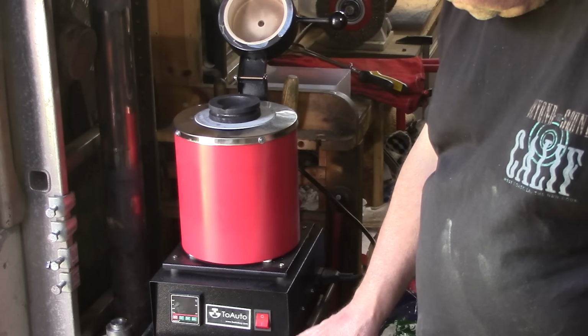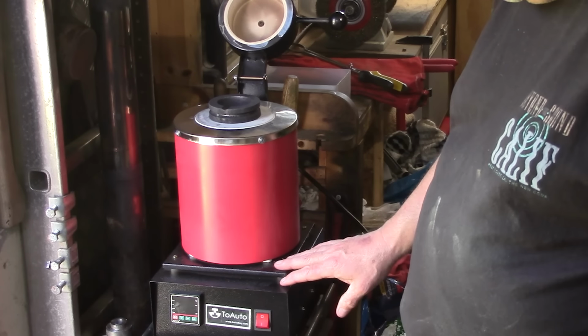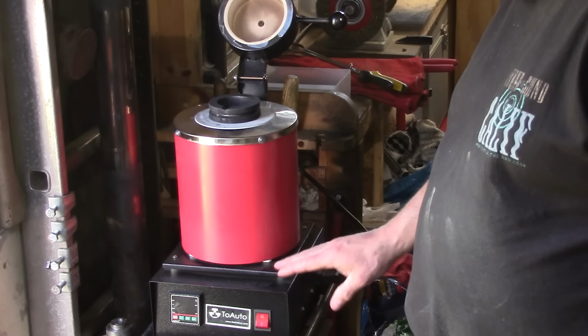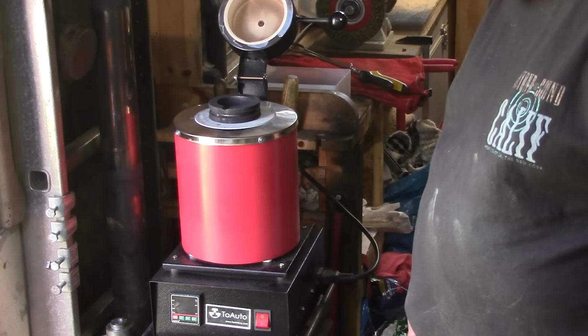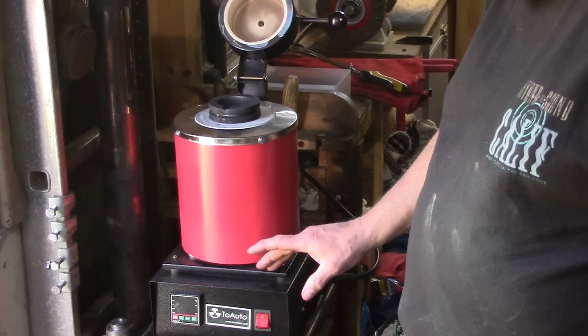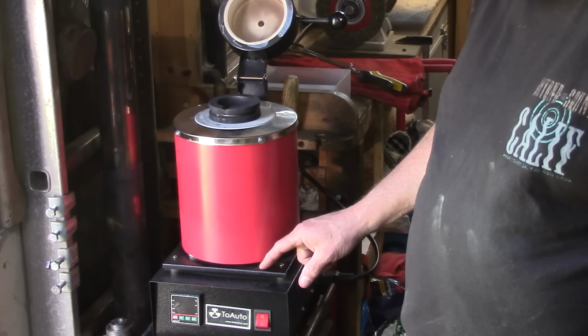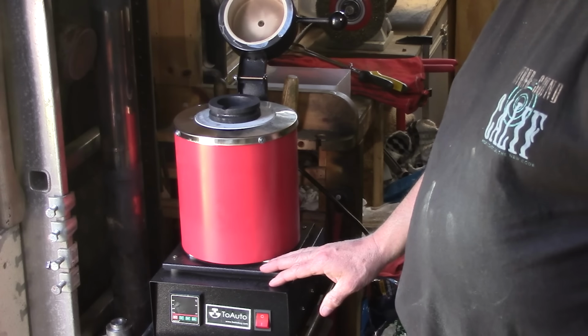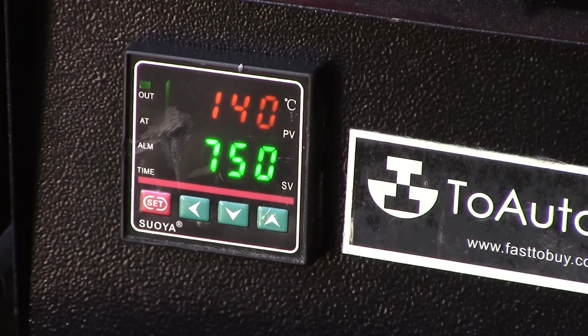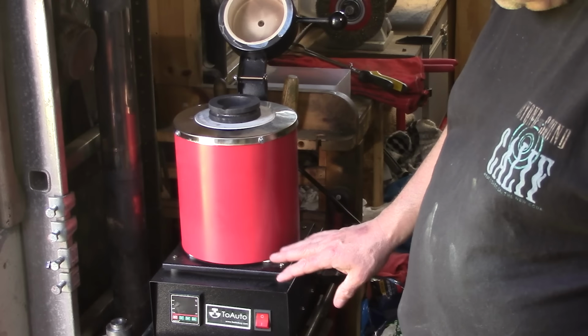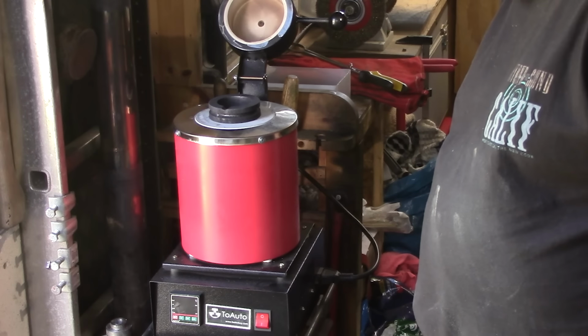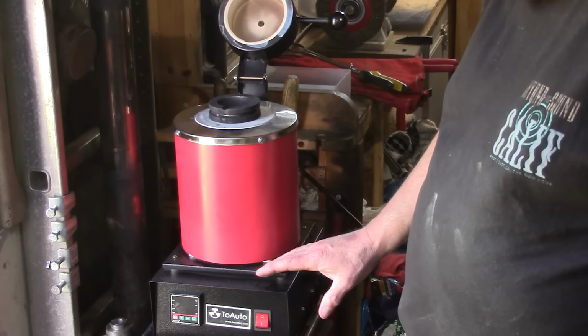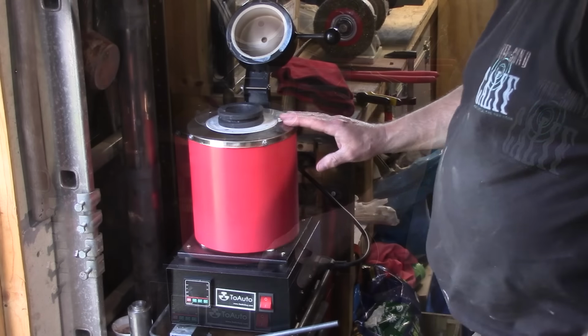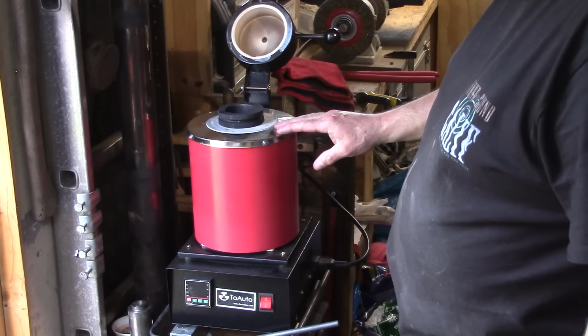The furnace is a nice compact unit which runs off a domestic power supply and is rated at 1.4 kilowatts, and its maximum temperature is 1100 degrees C, which is hot enough for brass, copper and bronze. It has a PID temperature controller which will automatically raise the temperature to whatever is set on the panel. These seem to be fairly generic Chinese furnaces and are available at varying prices, so do shop around for the best deal.